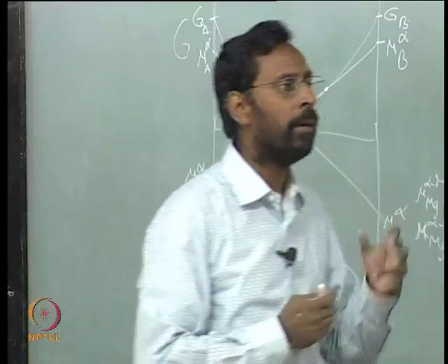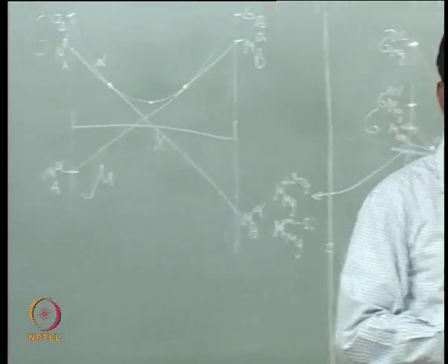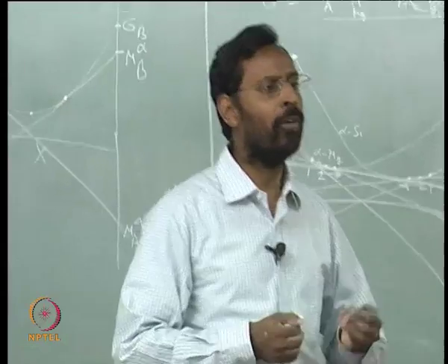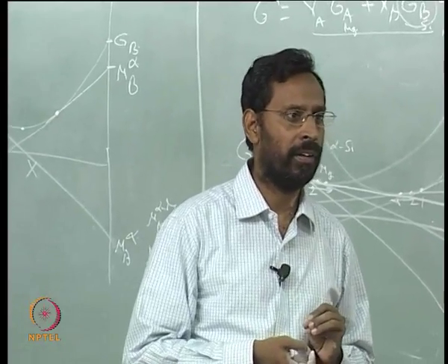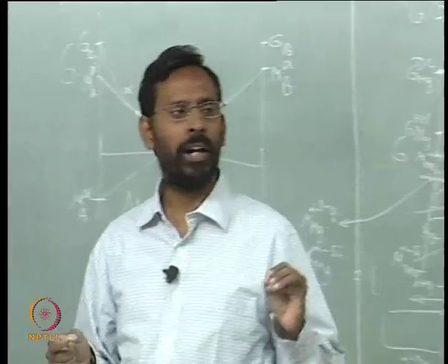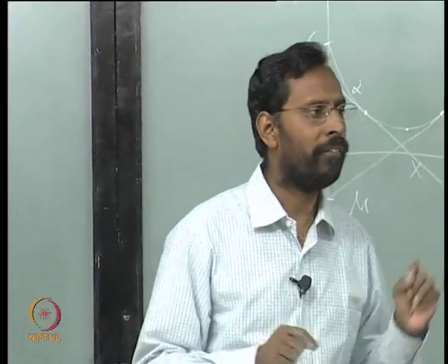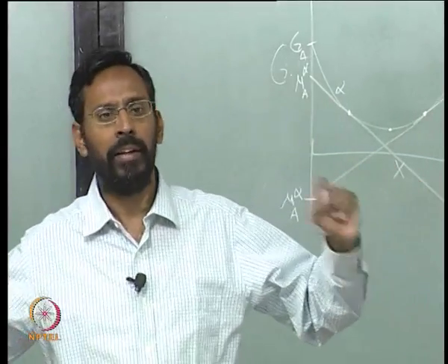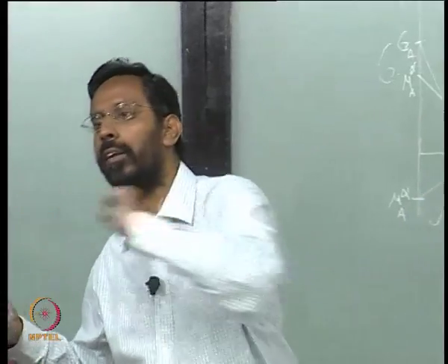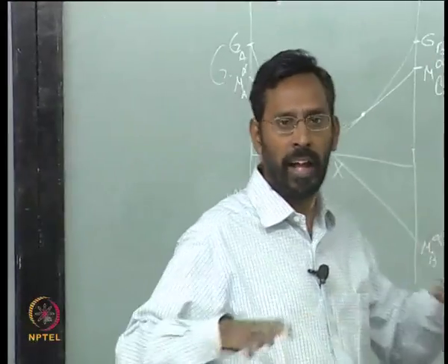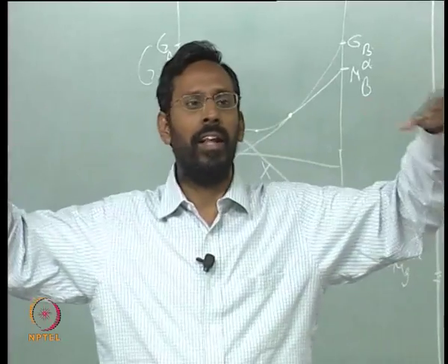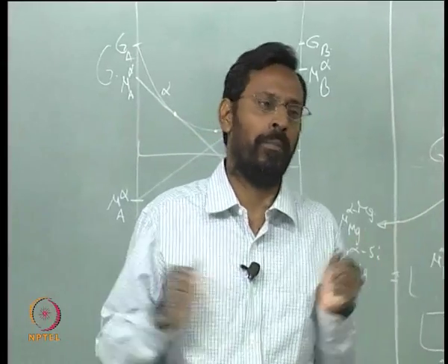In any multi component system, equilibrium is defined not simply by which has a lower free energy, it is defined by equality of chemical potentials, and when the chemical potentials become equal, then one element cannot move from one side to the other. Then wherever the elements are, they remain there, and that is thermal equilibrium.